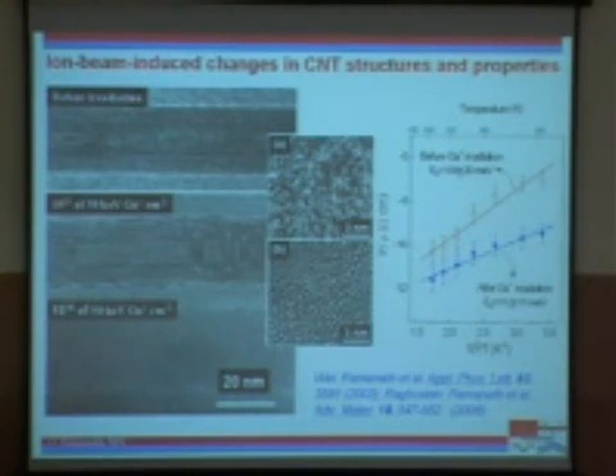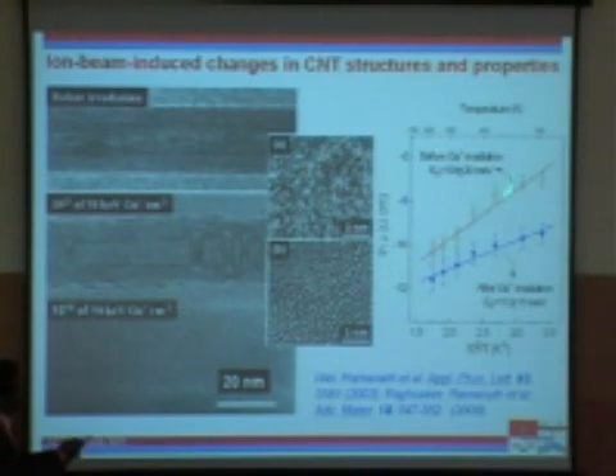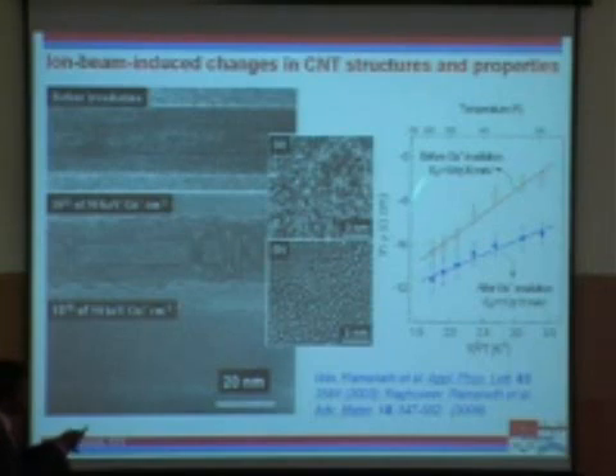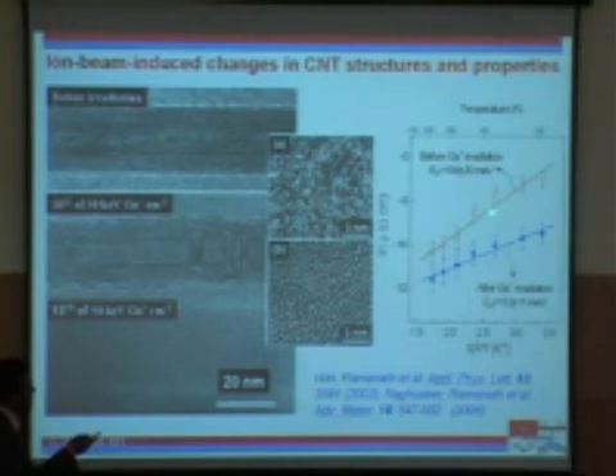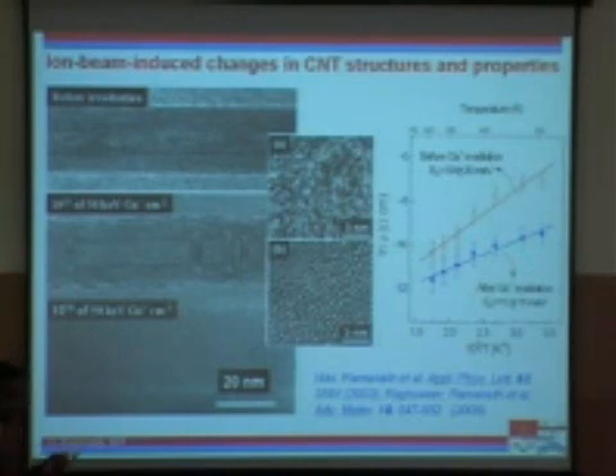So what happens to the electrical properties? Well, you can see over here that before radiation, the resistance versus temperature behavior has an activation energy of around 200 millielectron volts, semi-metallic basically. But after irradiation, it changes a little bit. But the thing is, you can do this controllably, as opposed to destroying the nanotube, which we do when you use acid treatments.